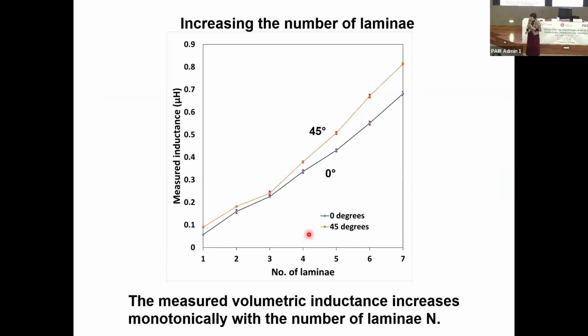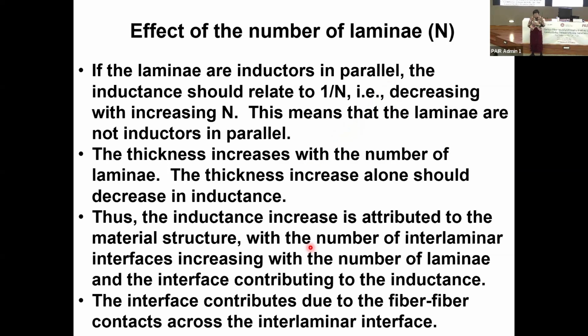And how about increasing the number of laminae? I was talking about one layer, one lamina. How about increasing that? Well, if you increase the number of laminae, the inductance simply increases monotonically, higher at 45 degrees than 0 degree. This effect is interesting. If the laminae were inductors in parallel, the inductance should relate to 1 over n, n being the number of laminae. And 1 over n means that the inductance would decrease with increasing n. But this is just opposite to what we see. We see the inductance increases with increasing n. This means that the laminae are not inductors in parallel.